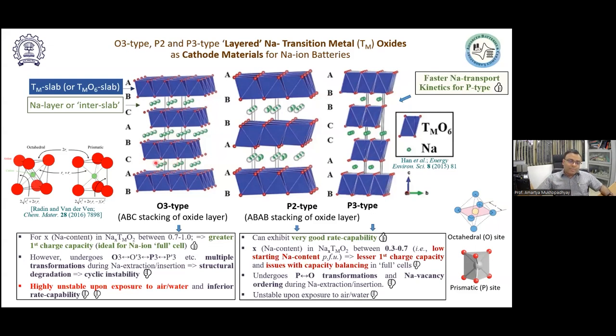Now, sodium ions being bigger in size, and since it has to go via a tetrahedral site, the sodium transport is quite sluggish in an O3 type of structure. So that's a disadvantage. Having said that, the O3 type of structure can form with a sodium content of 1 per formula unit, just like lithium cobalt oxide or lithium NMC, where lithium is 1 per formula unit. In an O3 type of structure, sodium content can be 1 per formula unit. Why I am saying that?